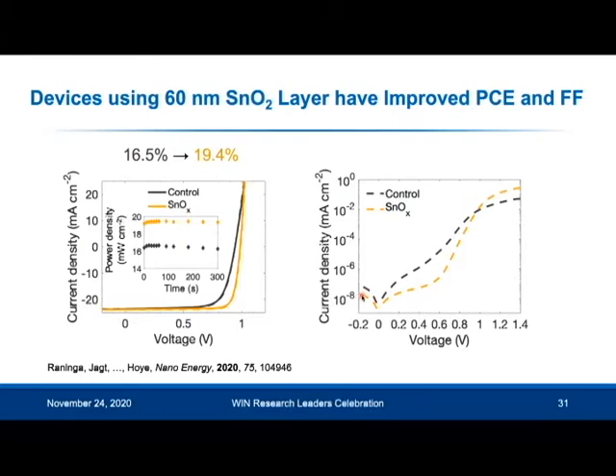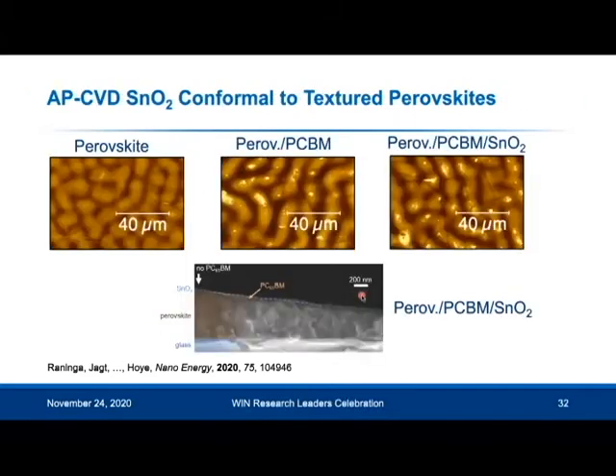But thus leading to improving the fill factor by increasing the shunt resistance. And very quickly, I just want to mention that we grew some textured perovskites, and we found that the tin oxide was conformal to that, which is important if we want to make a textured perovskite silicon tandem.